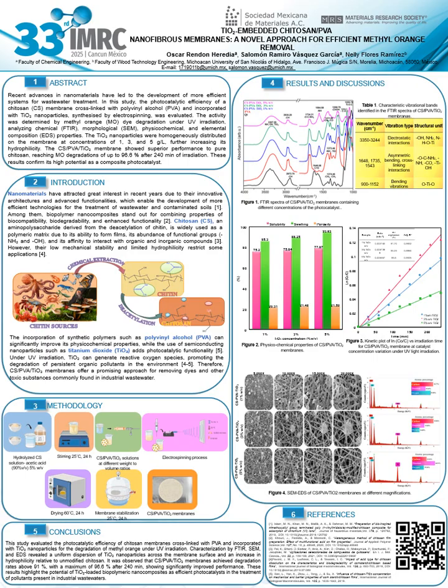Chitosan PVA nanofibrous membranes with embedded titanium dioxide nanoparticles were successfully produced via electrospinning, showing uniform fiber morphology and well-dispersed nanoparticles. Titanium dioxide significantly improved photocatalytic efficiency, achieving over 91% methyl orange degradation within 240 minutes, far surpassing pure chitosan PVA membranes. FTIR, SEM, and EDS confirm the structural integrity and strong nanoparticle anchoring, ensuring reusability and long-term stability. These membranes show great promise as sustainable, multifunctional nanocomposites for the treatment of industrial wastewater contaminated with persistent organic pollutants. Thank you so much for your attention.